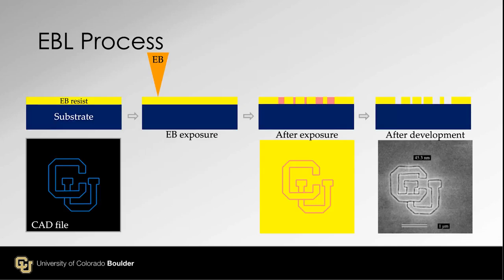Let's look at the e-beam lithography process. You have a substrate, silicon or whatever of your choice, and you spin coat e-beam resist, which is different from optical photoresist. And you start with a CAD file instead of a mask. Then you expose the e-beam resist with a focused electron beam. After exposure, the exposed area changes physically or chemically, depending on the e-beam resist you are using. But after exposure, it is still flat under observation. Then you use a chemical to remove the exposed area. I'm talking about positive e-beam resist here. Then you have a pattern in the resist, okay?